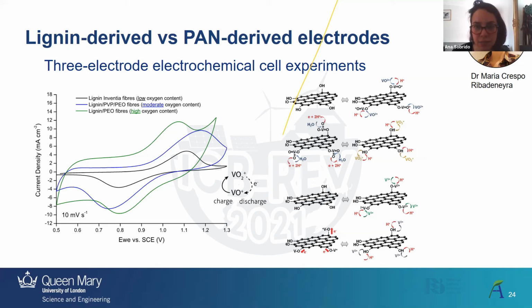As I was mentioning here, as you can see, in the example we are showing the OH. It can happen with other oxygen functional groups, and even others as well, as I will show in a second. And then you can see how the vanadium species will attach to the oxygen and interact with it to conduct the reaction of oxidation or reduction. So the presence of these functional groups at the surface is really key in trying to increase the performance and electron transfer of the vanadium species.